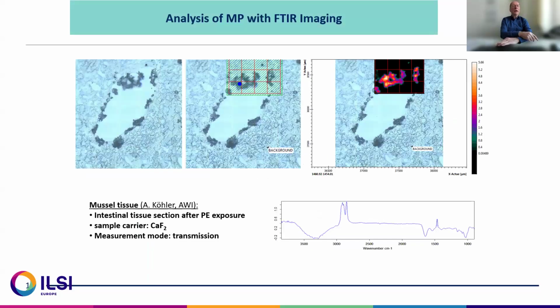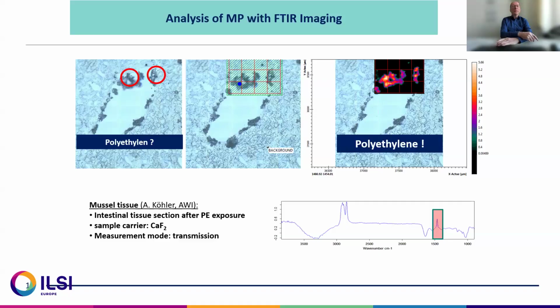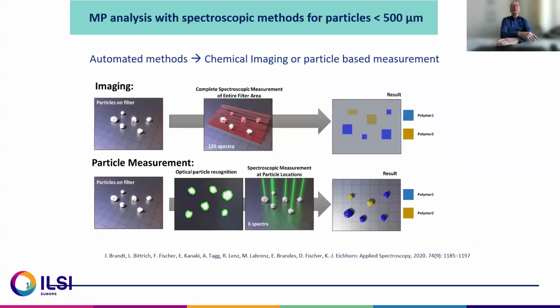This is shown here in a very short example. You have here a tissue from a mussel and some particles inside, and then on the right side the FTIR imaging, and you can see that in red are the spectra of polyethylene, and you can prove that by the spectra and found it.